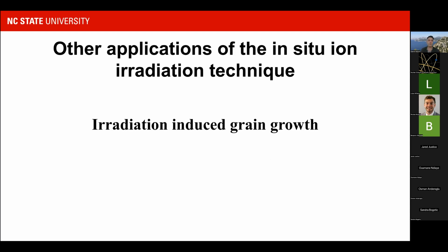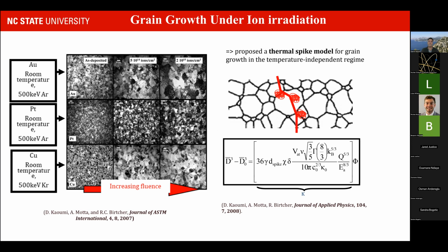So I gave a little bit of an example of how radiation damage can be studied through in situ irradiation in the TEM. I want to show another application. This is a more fundamental study on how irradiation impacts the grain size of metals. In such a study, we were looking at nanocrystalline metals, pure metals for that matter, that had an initial grain size of about 10 to 15 nanometers. And we're looking at how the grain size and the grain size distribution were affected by irradiation.